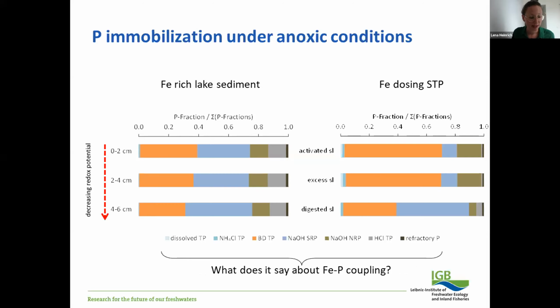And these conditions are mimicked by the reducing agent bicarbonate dithionite with a subsequent digestion of phosphorus compounds to orthophosphate, which is then analyzed. And the blue bars here and here indicate phosphorus that is released by a 1 molar sodium hydroxide. And this indicates phosphorus that is bound to, for example, redox stable iron oxides and Vivianite, that was not dissolved by the previous reducing step. So therefore, the design of the fractionation scheme is helpful to determine between the redox sensitive and the redox stable iron bound phosphorus in iron-rich systems.